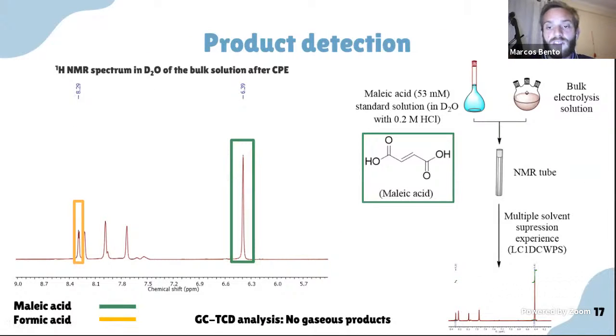For the detection of the products, firstly, we analyzed the headspace of our electrochemical cell through GC-TCD, and we didn't see any kind of gaseous products from CO2 conversion. By the analysis of the bulk electrolysis solution with maleic acid standard solution and using a multiple solvent suppression experiment, we detected some formic acid that was formed during the electrolysis.